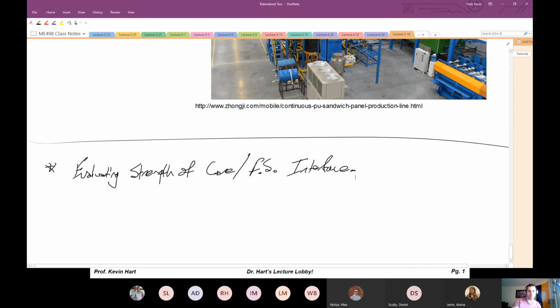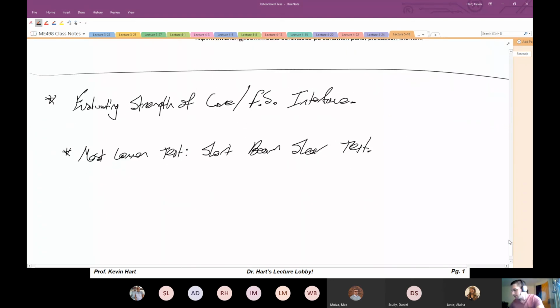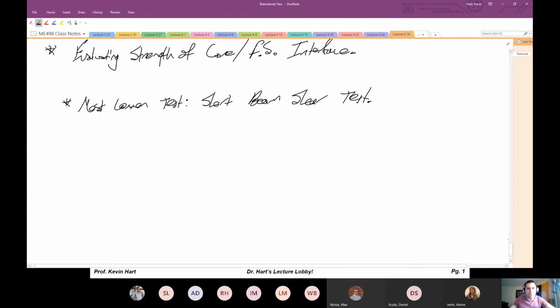All right. So I don't have a lot of time to get into this here, but I'll say the most common test that's done in industry to evaluate the strength of the interface is what's known as the short beam shear test. With the short beam shear test, you make a sample that is very short. The idea is that you have a 3-point bend sample with a short span. And what happens when you shorten the span is that the bending is minimized and the shear is maximized.